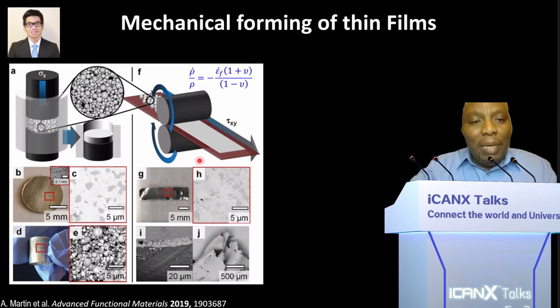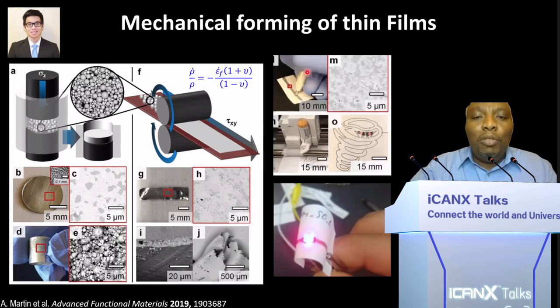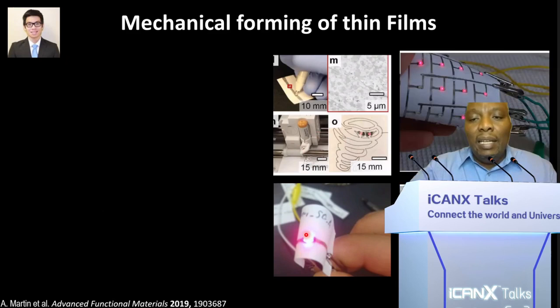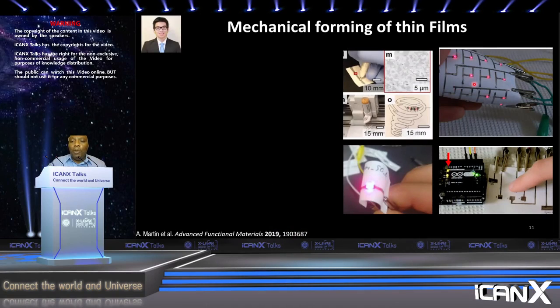Now, if we can mechanically densify and solidify these particles, because once you break the shell, the particles will basically solidify immediately, we can formulate them into inks, which you can draw by hand, or you can use a robotic arm to draw. And here we're just drawing on pieces of paper. And you can see even once you form those lines and you bend it, it's still very conductive. And beyond that, we can actually build bigger structures like this display system here. We can make touch pads out of this metal. And these are forming very thin metallic films on the surface.